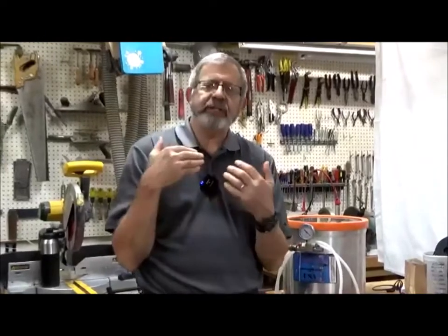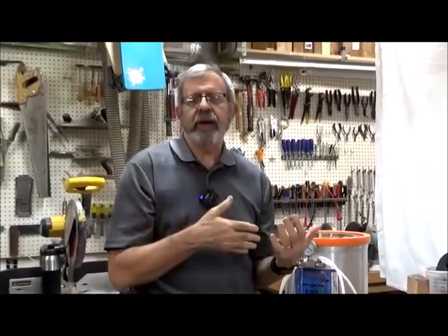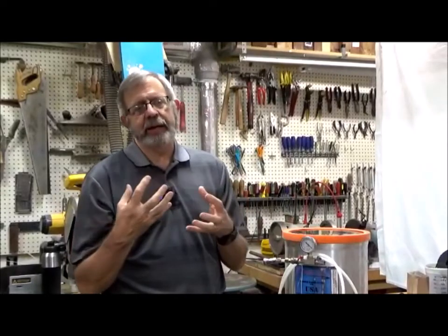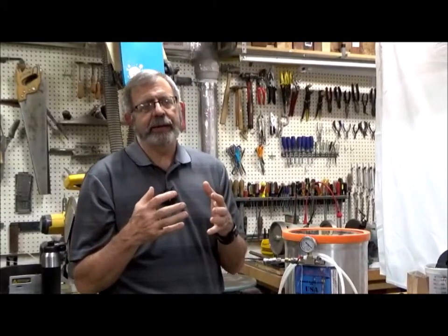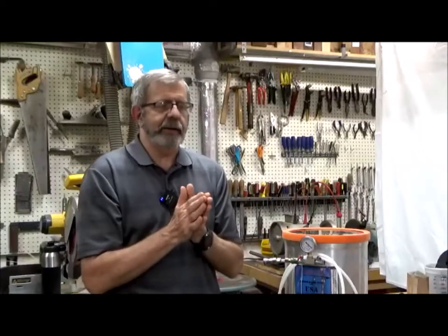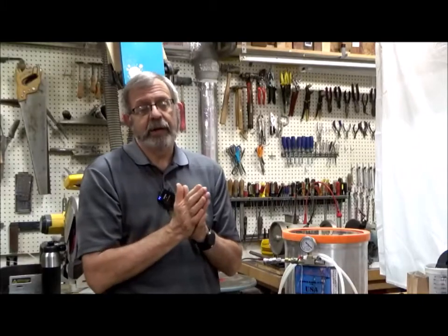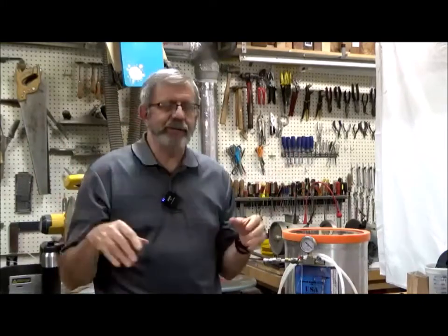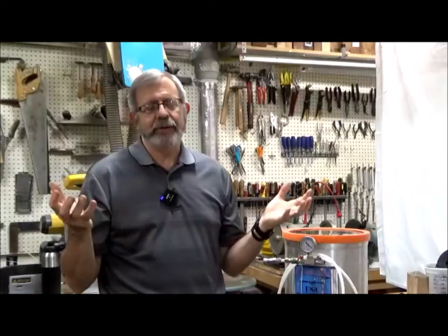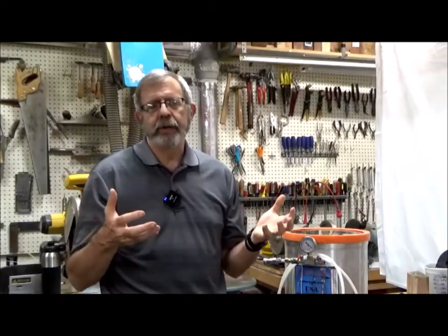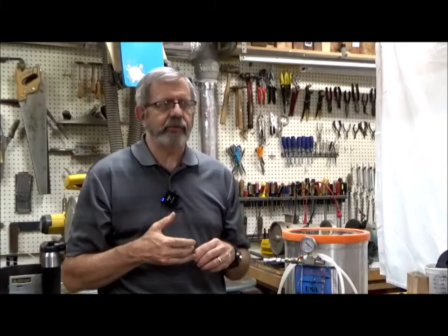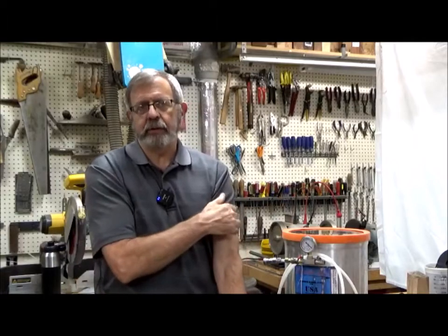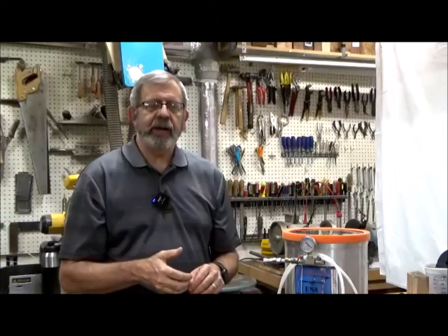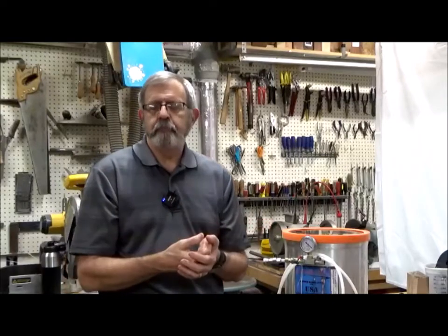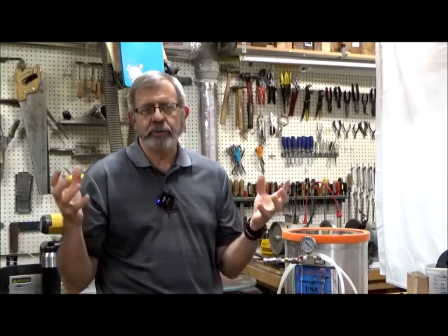And then finally, the wood has to be dry before you put it in the vacuum chamber. If you don't do that, you're trying to displace water, and it contaminates your resin, and it doesn't work nearly as well. So what I do is I'll take my blanks and just throw them in. I don't worry about checking moisture. If it's air dried, you don't do it at all in green wood, but if it's air dried wood, I put it in the oven at 250 degrees for 12 hours. I let it cool before you put it in your vacuum chamber. I found that to be dry enough for anything we need to do. And again, I'm not doing big pieces.